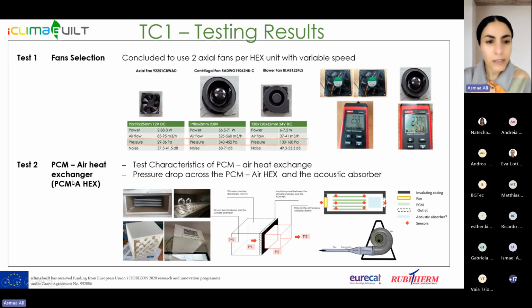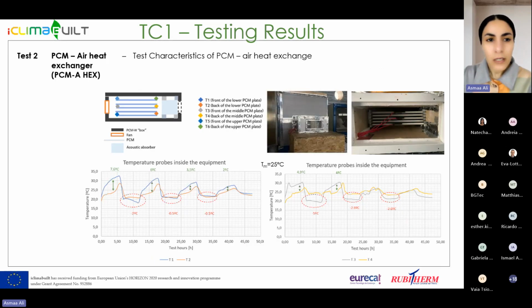Coming to the second test, of the PCM air heat exchanger, we tested both thermal performance and pressure drops. As you see here, this is the first unit that was fabricated, and here is how it's seen from inside. You see the 2 fans in series, and the PCM plates. For every unit we have 5 plates parallel to each other, and finally we will have the acoustic absorber, as you see here. The thermal performance was tested in a climate chamber at EURECAT, and here you see the sensors distribution, and this is the setup of the acoustic and pressure drop tests across the heat exchanger and the acoustic absorber.